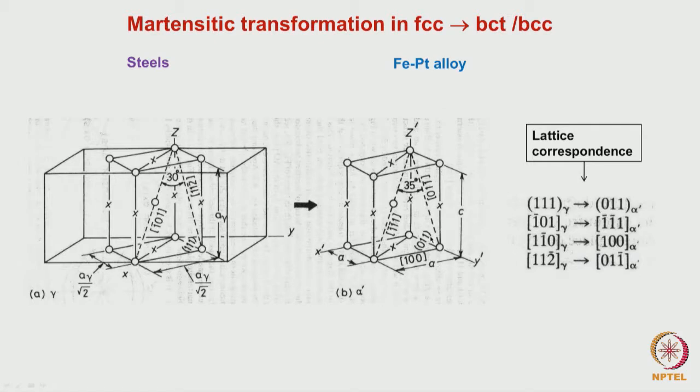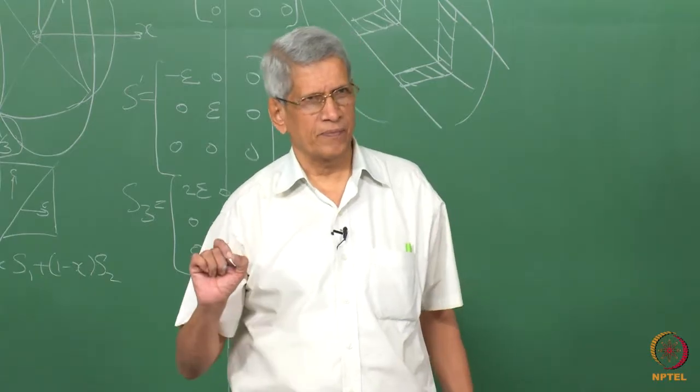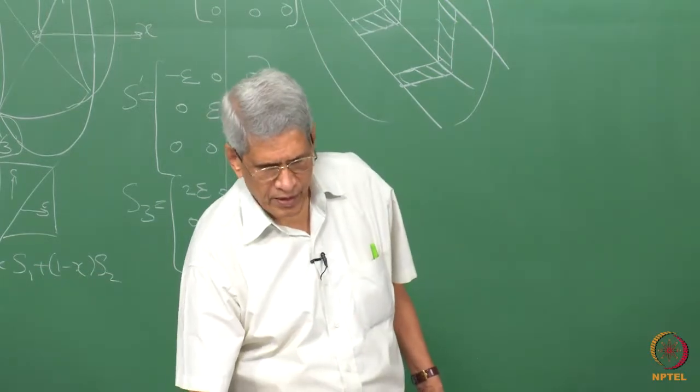When we consider a rotation, a slight tilt will take place. Because of that, some tilting might exist between these planes, which is essentially equal to one rotated from the other by the tilt angle. That is what we see in the orientation relationship, the small differences also. The crystallographic theory of martensitic transformation could explain all these differences exactly. This much is clear.